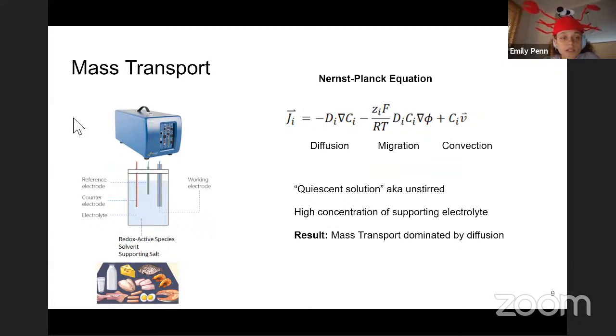The third thing that we need to consider is mass transport. And the main equation that we'll use for this is the Nernst-Planck equation. So the Nernst-Planck equation has three components to describe the three different modes of mass transport. So we can relate the flux of some species i to the diffusion. So that's related to the concentration gradient. And then we have the migration component, which is related to the potential gradient. And then we have the convection component if we happen to be stirring our solution in any way.